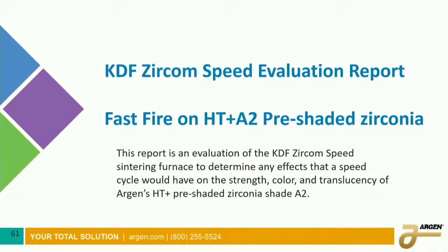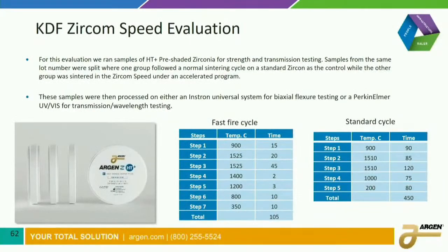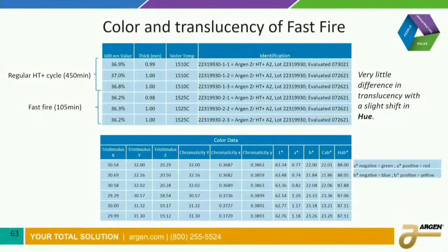And here's our evaluation report. Now what we did here, we tested for the strength of the material as well as the translucency of the material. Okay. So first we just take our regular material and we do a standard cycle, which is like 450 minutes, and then a fast cycle here is 105 minutes for this particular product. Now we look at the color and the translucency of the material, and we see for the regular cycle we're like 37%, and for the fast fire cycle we're at 36%. So that's not bad. Again, this is a colored material, so you're not going to get a full 45% translucency. But the results are not bad comparing the two.